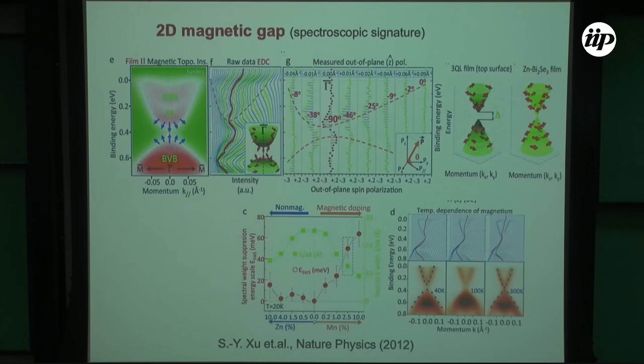Now here, the measured spin texture is based on this data. We're drawing these arrows, this kind of 3D thing. If your Fermi level is here, then you have a net spin polarization on the surface, right? So clearly it's not time reversal symmetric, it's broken. This is our diagnostic: instead of clearly identifying a gap, if we find that the surface state spin texture breaks time reversal, then some sort of magnetism must be there, and that magnetism should have some global component.